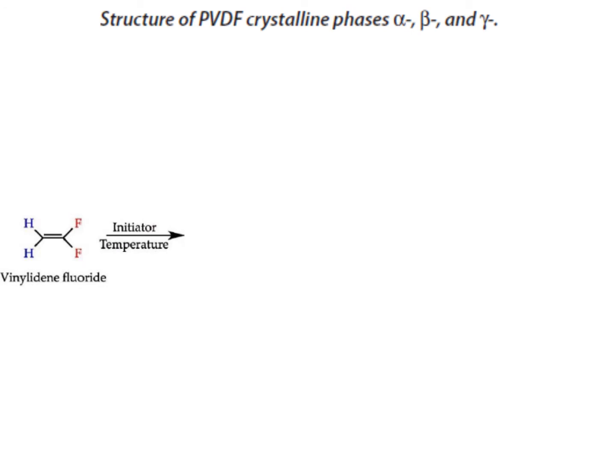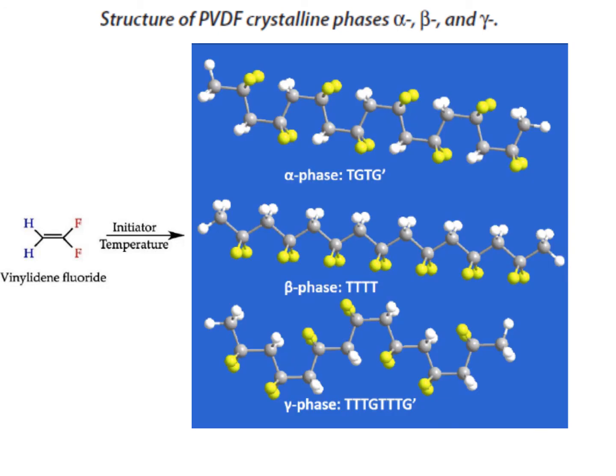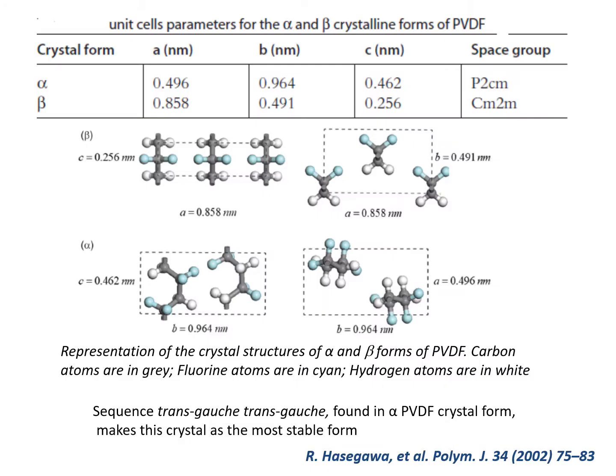So VDF can be polymerized under radical conditions and leads to PVDF, in which, as has been well reported today, there are alpha phase, beta phase, and gamma phase. Thermodynamically, you can get the beta phase, but kinetically you have the alpha phase as major after polymerization. You have a wide variety of alpha phase in the medium with gamma and beta, and also delta and epsilon. So the point is, as this is a crystalline polymer, it is required to investigate the unit cell parameters.